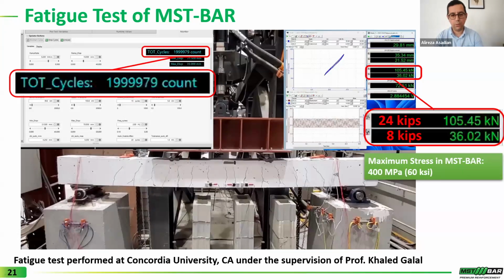beam was under fatigue loading at a frequency of 2 Hertz, meaning 2 cycles of loading and unloading per second on this beam. So this beam survived 2 million cycles of loading and unloading, and then the test was stopped since no failure was observed. And here are the last few cycles of that beam test.